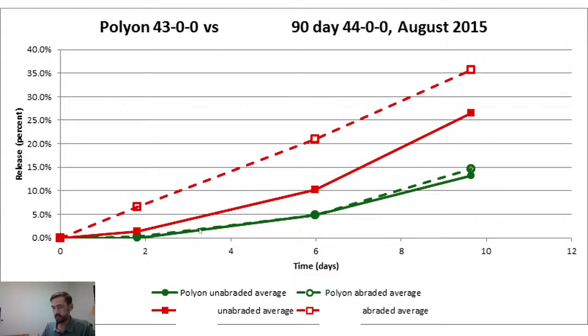And what you want to see is that there's a nice tight correlation, there's a nice tight trend between the release of a material before drop and after drop. So before drop, that's the material fresh off the manufacturing line, has not gone through the drop test, and that's represented by this solid green line. So that's Polyon just after it was manufactured. In comparison, the dashed green line, this is Polyon after it's gone through the drop test or the abrasion test. And you'll notice that there is a very tight correlation between the before drop and after drop results. You see a slight deviation here 10 days after the drop test. But relatively speaking, that's a pretty tight correlation there.